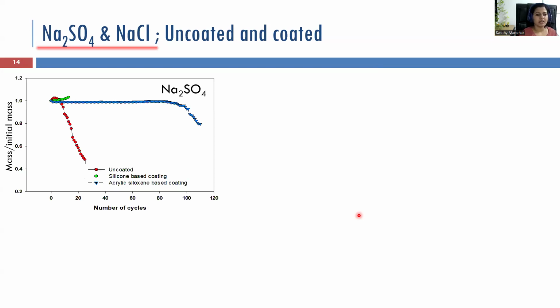We also compared the behavior of the bricks with different salts, sodium sulfate and sodium chloride. Also, we looked at the efficiency of different coatings and uncoated samples. Here, the sample which has small pores and is more susceptible to damage is coated with two different coatings, silicone and acrylic siloxane based coating.